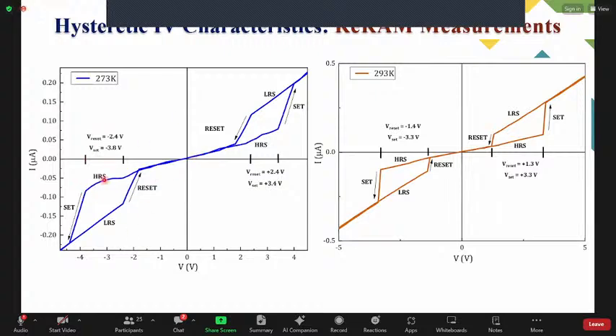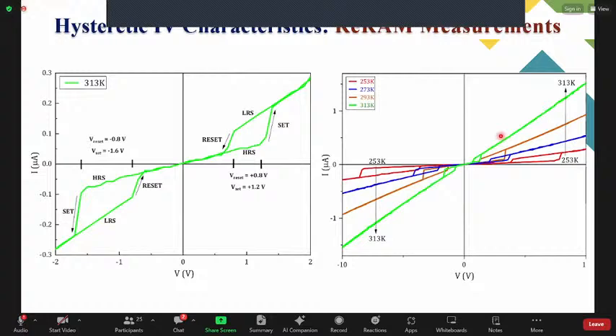So for 273 Kelvin, again we can see that set reset voltage is getting decreased again. This is for 293 Kelvin. The current value is in microampere. You can observe here for 313 Kelvin. And this graph shows for all the temperature variation together. So we can see that for 313 Kelvin, the current is highest, and for lower temperature, the current is lowest. So this shows that semiconducting behavior.